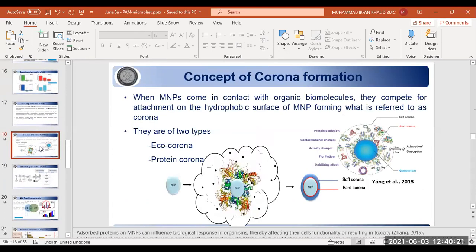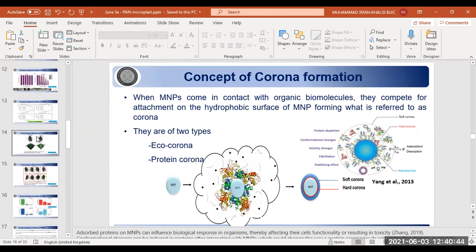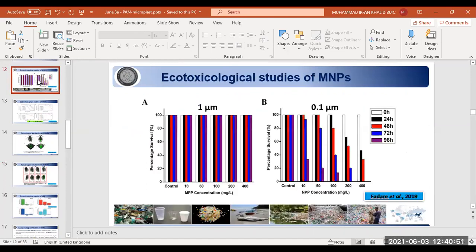And in the work we did, we found that small polystyrene particles were quite toxic to Daphnia, as you did. But similar sized particles made from more polar polymers were not toxic at all in 72-hour immobilization assays anyway. So I think there are some really important and subtle differences here dependent on the type, nature and surface properties of the plastic.